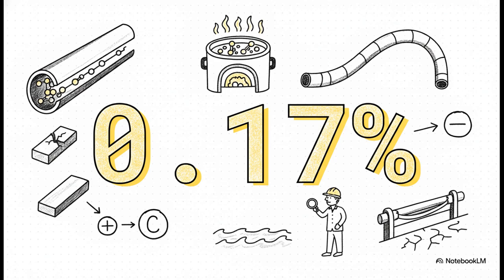To put into perspective just how precise this has to be, let's look at the number 0.17%. That tiny fraction is the absolute maximum allowable carbon mass fraction for high-strength, extreme-strain pipe grades like X80. If you add too much carbon, the steel becomes way too brittle and won't bend. But if you have too little, it loses its structural strength. So pipeline engineers are effectively custom-baking this steel at a molecular level just to perfectly balance strength and flexibility. They are literally preventing environmental disasters before they even have a chance to happen.